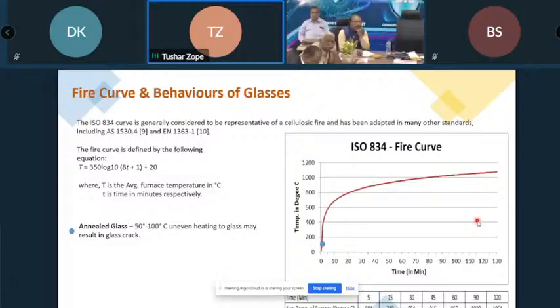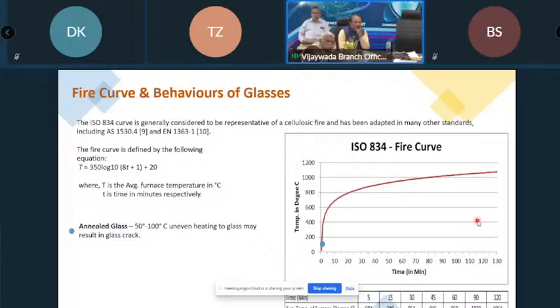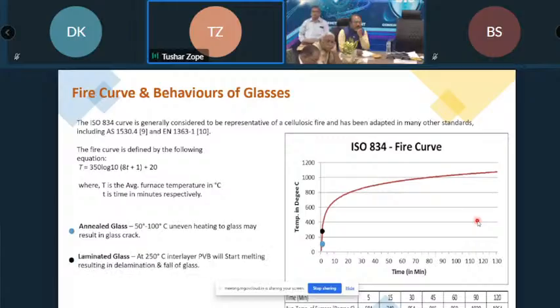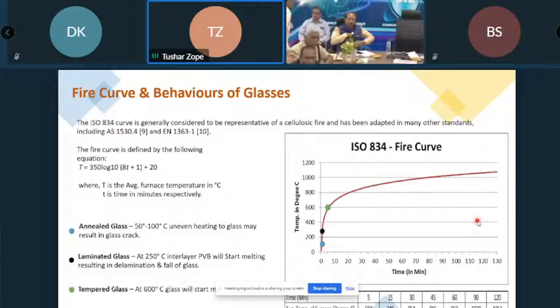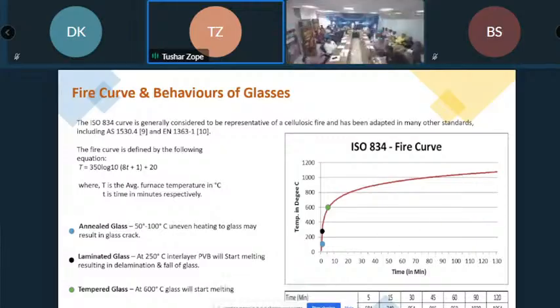So what if we use an annealed glass which is exposed to such a high temperature? This annealed glass will break when it is exposed to an uneven temperature of 50 to 100 degrees Celsius. The laminated glass, which has polyvinyl butyral, which is a plastic material, will get delaminated after 250 degrees Celsius, and the glass will fall. So the purpose of maintaining the integrity will not be served. Another option is to use a tempered glass, which also changes phase after 600 degrees Celsius.